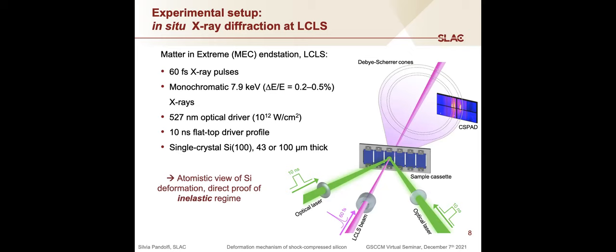It's very noisy here. So this actually ensures that as soon as we do see some signal, this signal is only from the compressed region. So this is our way to clearly distinguish this, and we don't even need to go in the perpendicular geometry because we know that our signal only comes from regions that have already undergone shock compression. I hope this answered the question, and I hope that was the question and the study you were referring to.